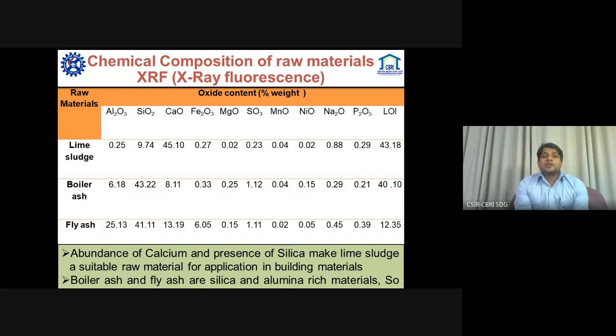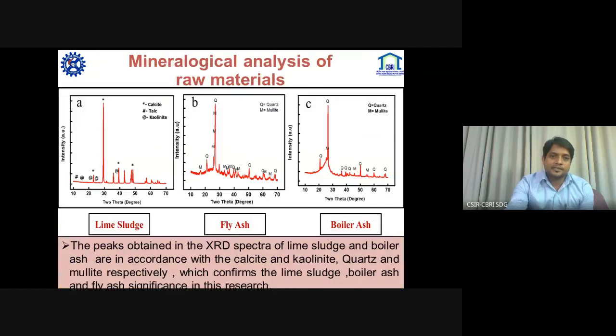And the boiler ash is majorly silica, present with 43.22%, and alumina with 6.18%. The abundance of alumina and silica makes boiler ash and fly ash a good precursor to synthesize nanosilica from.